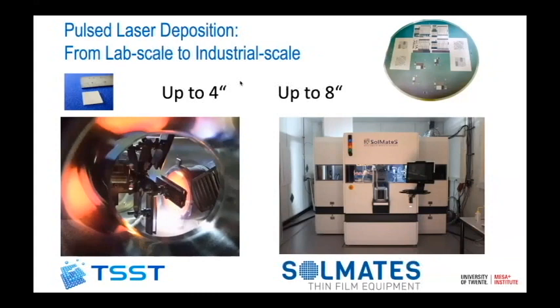Typically, these pulsed laser deposition tools are used in a lot of laboratories where you would deposit materials on a 5 by 5 square millimeter sample or so. But nowadays, with these tools, we can even go up to a 200 millimeter wafer scale. And that is quite promising for getting our materials into production and into real devices.